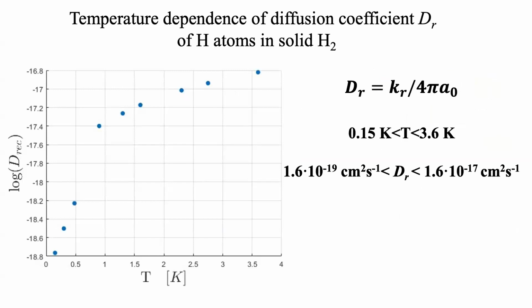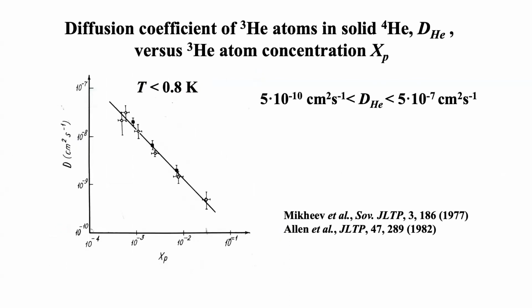In this temperature range, we place the logarithm of diffusion obtained from recombination versus temperature. This diffusion coefficient is in the range between 10 to minus 17 to 10 to minus 19 centimeters squared per second. At the same time, it was known, for example, in the case of helium-3 in solid helium-4, their diffusion coefficient for helium-3 is in the range 10 to minus 10, 10 to minus 7. So it's like 10, 12 orders of magnitude faster, helium-3 moving in helium-4 than H in H2.